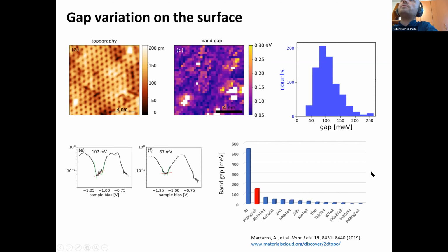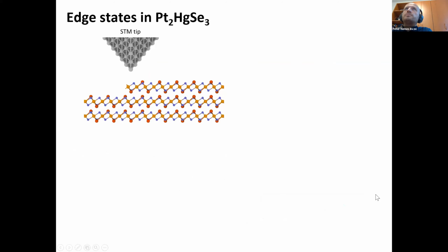So if you compare this band gap to other 2D topological materials, like in this website that has been done by the EPFL group, you can see that this is quite large with respect to other 2D topological materials. So it's only surpassed by the monolayer of bismuth, basically. So this looks quite promising from this point of view.